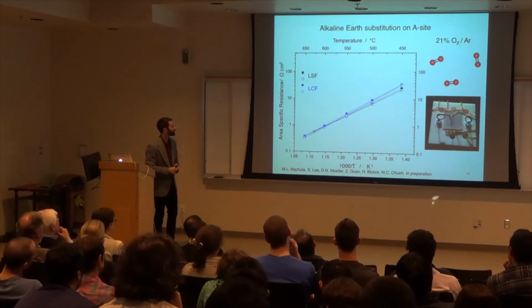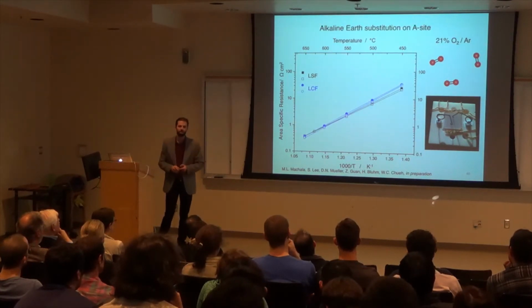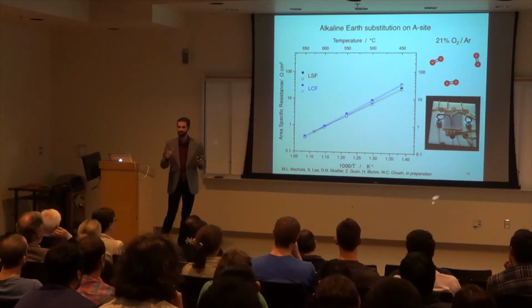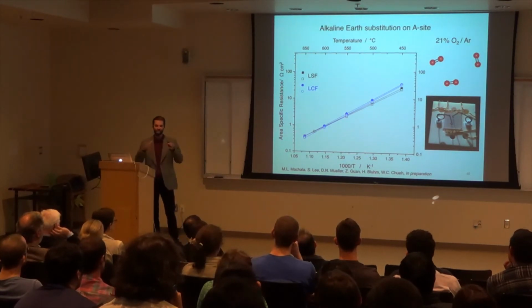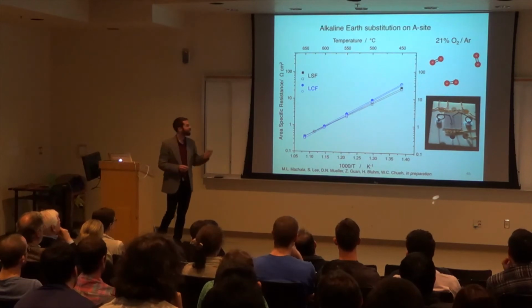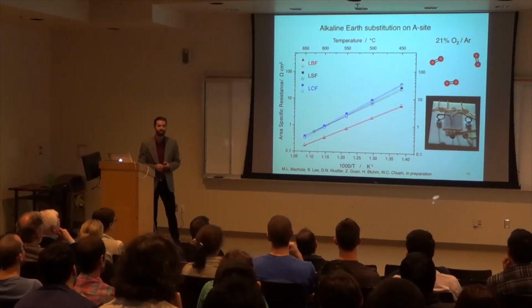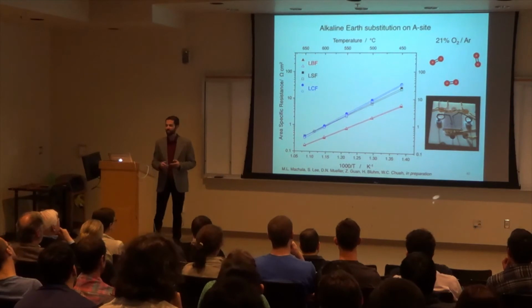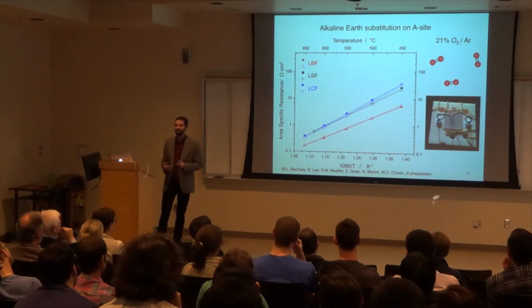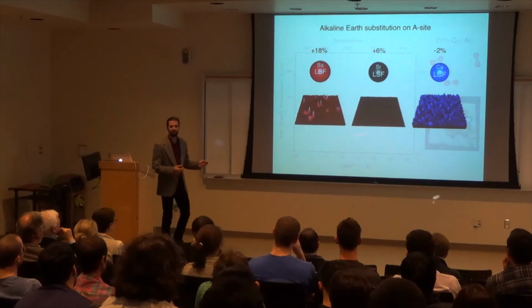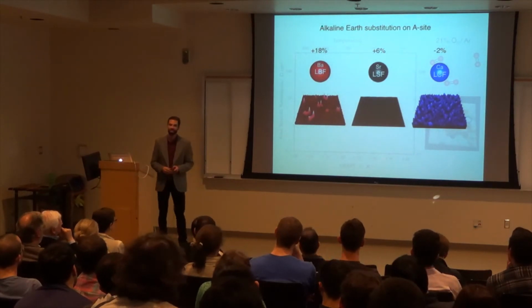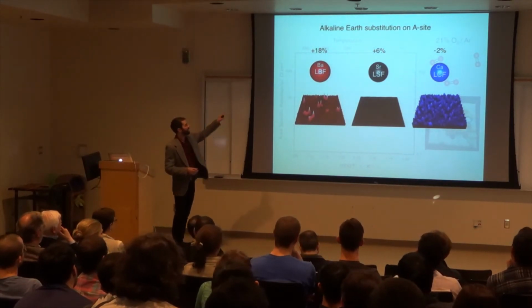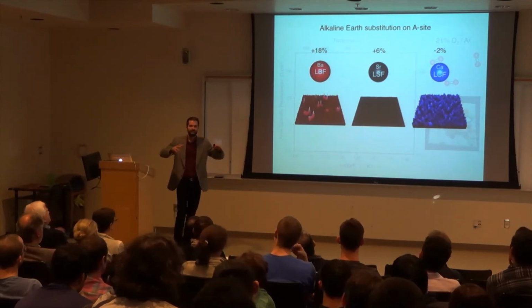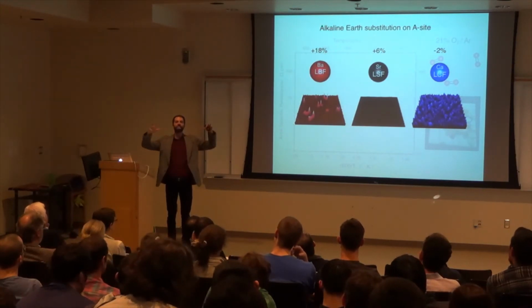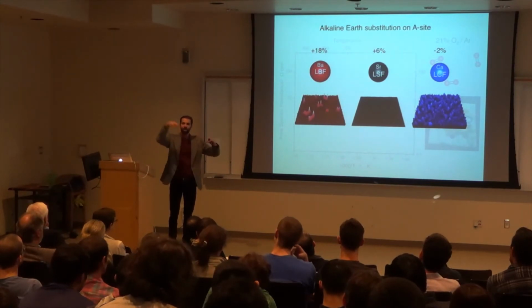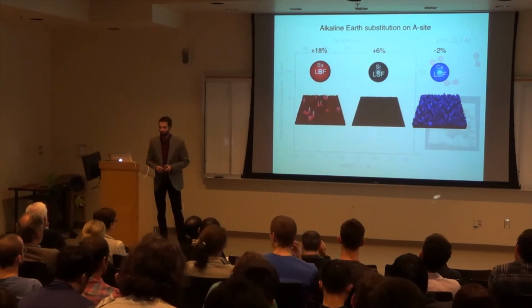When we look at the calcium, we see that it overlays it pretty well, which is kind of confusing initially. And we did something different, and we tried to change the lattice size. When we went down to barium, we were surprised to see that it has the best catalytic activity. And this is confusing because we thought we had all these precipitates on the surface blocking catalytically active sites. But you can remember that the ionic radius also has an effect in the lattice. Essentially, you can imagine expanding the lattice out so that oxygen can hop into it much easier, lowering the kinetic barrier for the reactions to occur.